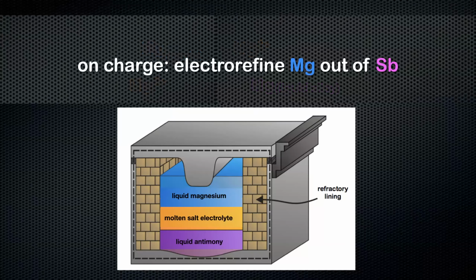And then to charge the battery, you force current through the cell, and that makes this into an electro-refining cell. So now the magnesium comes out of the antimony, goes across as magnesium ion, and then becomes magnesium metal on the top. And you restore the battery to its pristine initial condition.